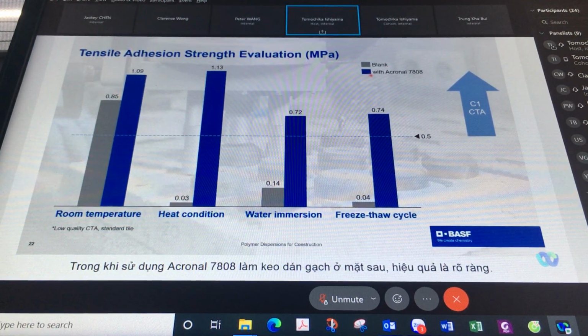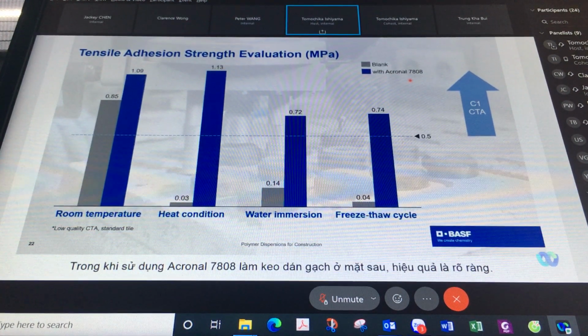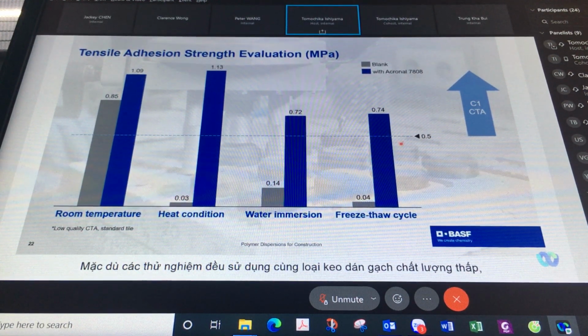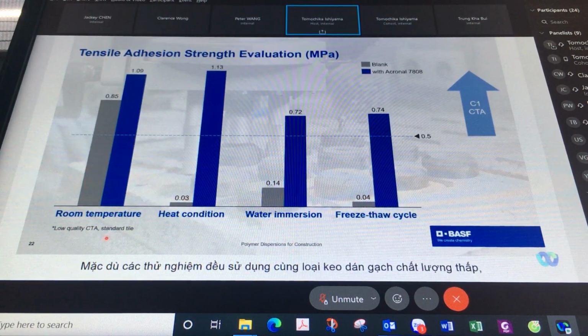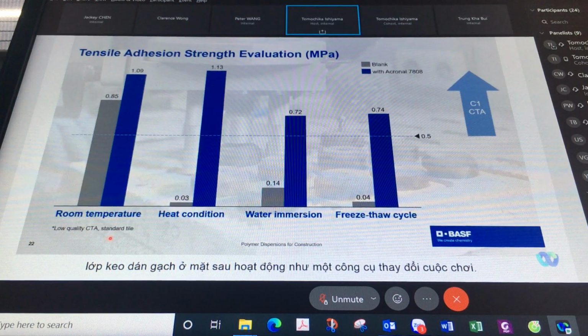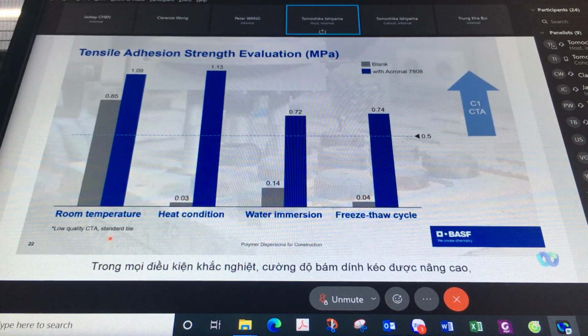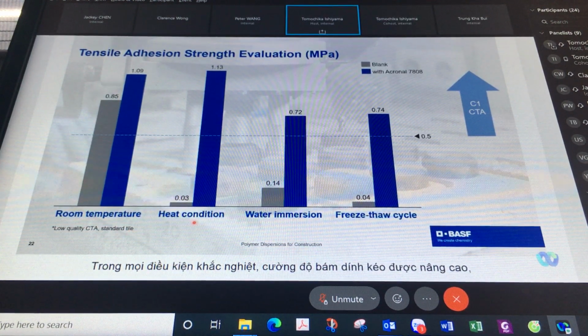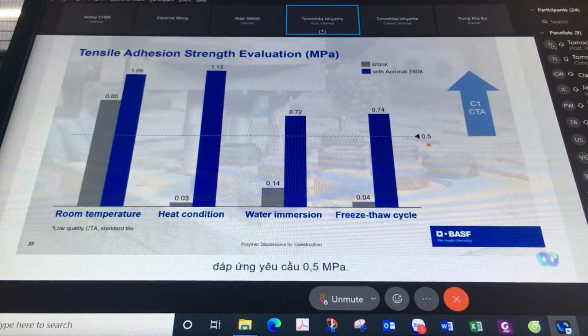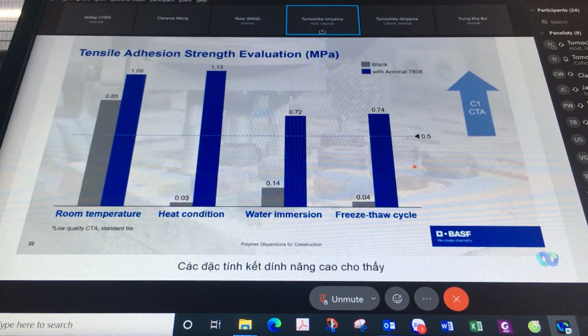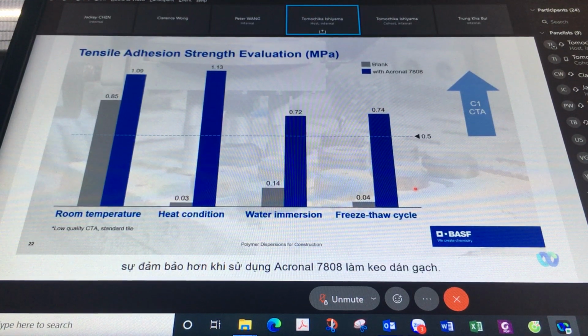While using Acronal 7808 as back-tile adhesive, the effect is obvious. Although the tests use the same low-quality tile adhesive, one single layer of back-tile adhesive behaves as a game changer. Under all conditions, the tensile stress is highly enhanced, meeting the requirement of 0.5 megapascal. The enhanced adhesion properties exhibit the greater assurance of using Acronal 7808 as back-tile adhesive.